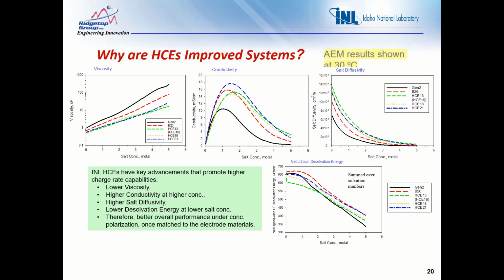That depletion on the anode side forces the desolvation energy to be higher, because you're always going to be progressing along those curves. If you go to the very bottom curve here on the right, as you deplete the electrolyte on the anode side, you're climbing that curve toward the left. And so you want the lowest desolvation energy possible with your choice of electrolyte at that point. The one shown in green, the HCE 13, has desolvation energies that are at least 10% lower, if not 15%, than some of the other choices shown. That tells us automatically this is going to be a good HCE for fast charge systems. Okay, next slide.